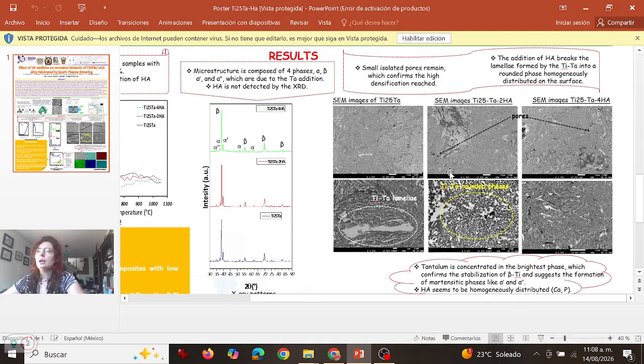And in here, I'm going to present you the same images. The images were obtained from the scanning electron microscopy. All right, so in here we have the images for the Ti25 tantalum. Here are the SEM images from the Ti25 tantalum with 2% of hydroxyapatite, and in here it's for the alloy with 4% of hydroxyapatite. So in here we have the images from the electron microscopy, and here is basically a zoom. It's the same image but with a zoom in.